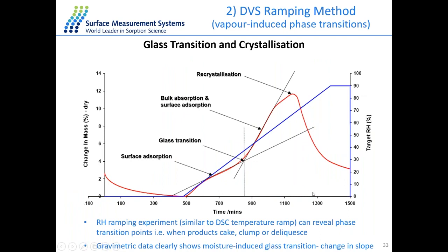Another thing we can do instead of the step method is using a ramping method. In this case, we've taken our material and dried it for 500 minutes, and then carried out a single relative humidity step over time, so a change of relative humidity over a set period of time. This is a ramping method, similar to the DSC temperature ramping method, and is really useful for understanding the glass transition phases and crystallization of a material.